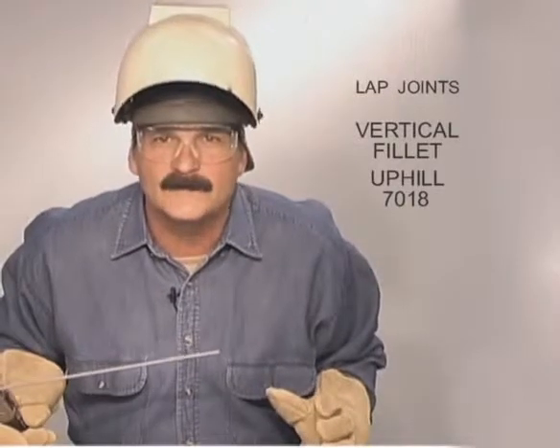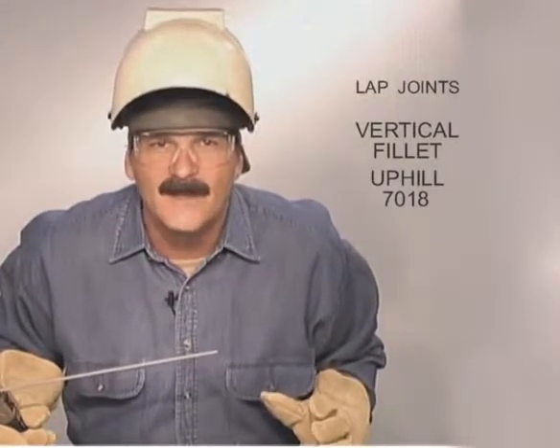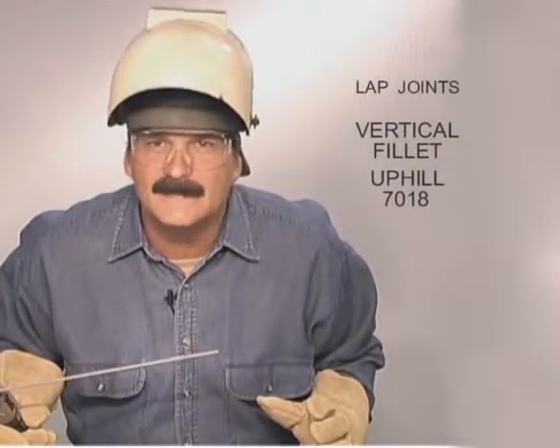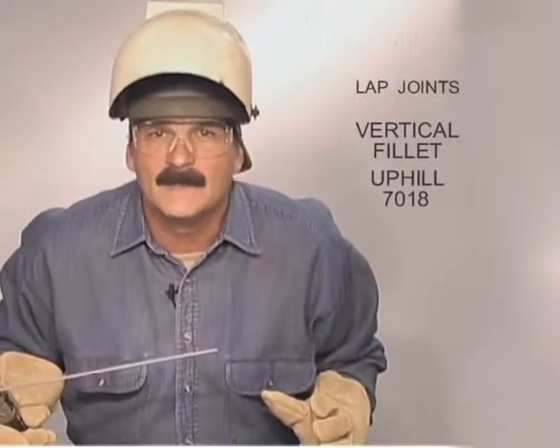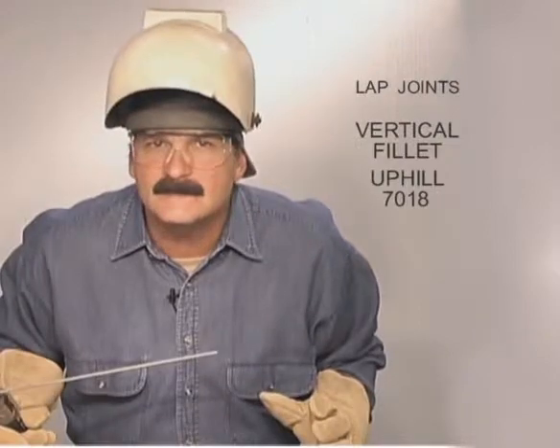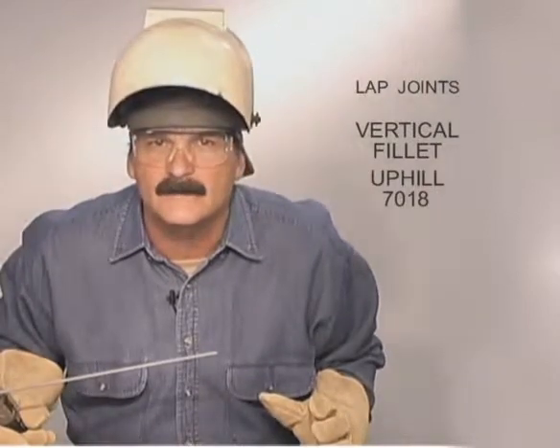You aren't going to build up a lot of weld on a vertical down, so you'll probably need to run a second pass. Vertical up with 7018 will not only provide a stronger weld, you can also build up more filler metal in one pass. Always keep in mind that 7018 is very sensitive to the arc gap. You don't want to jam the rods into the sides or long arc across the center.